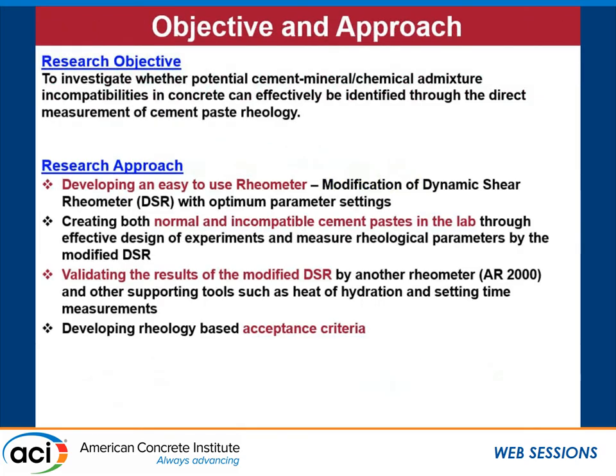The objective was to investigate whether potential cement, mineral, and chemical admixture incompatibilities in concrete can effectively be identified through the direct measurement of cement paste rheology. The other speakers already talked about the chemistry and mechanism behind it — I'm just talking about the practical test. The approach was to modify the dynamic shear rheometer, apply it to measure cement paste rheology, determine whether it can distinguish between normal and incompatible mixes, and then validate the results using a more advanced rheometer. We also developed acceptance criteria to give the DOT the range of what is normal and what is not normal.